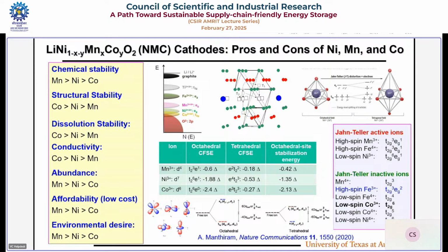How is it? Cobalt is good for that. Manganese is bad for that. Exactly, too bad, diametrically opposite. Third, any time you have electronic configuration, 1 electron in the EG band or 3 electrons in the EG band, it will have something called Jahn-Teller distortion. Physics people know that. That means instead of being cubic symmetry, then you will have like this. If you have 1 electron here, if it goes from cubic to tetragonal, that 1 electron can sit at a lower energy, so it will automatically tend to go from cubic to tetragonal. I call it electronically driven lattice instability. That's what is driving here.